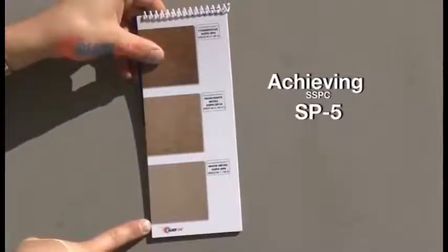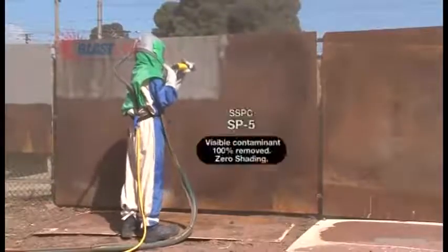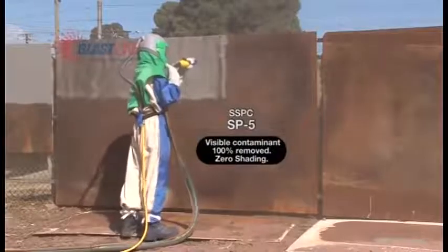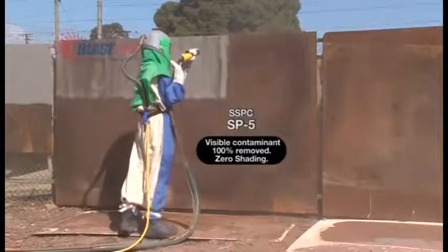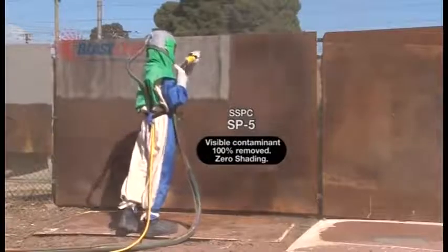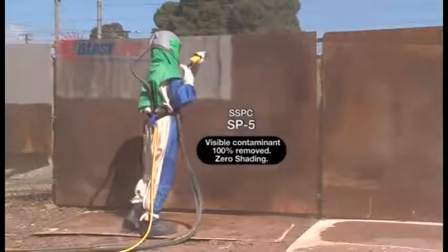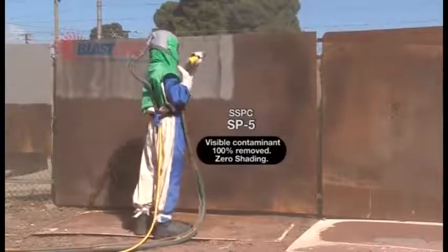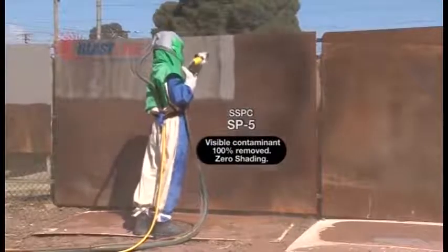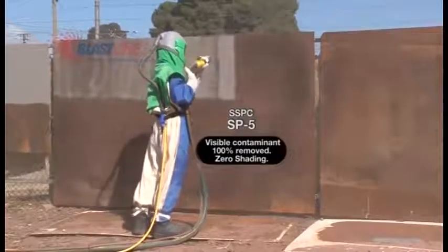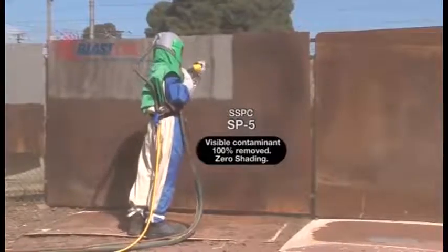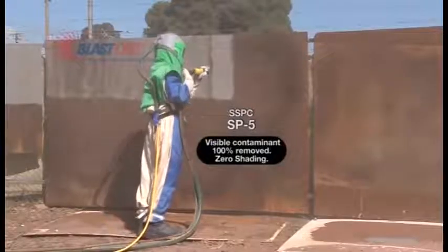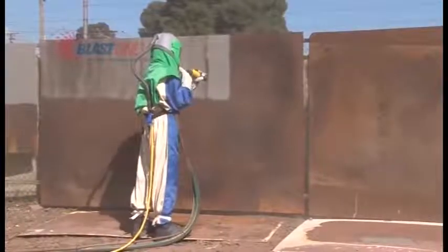How to achieve an SSPC SP5. The specification for SP5 requires a clean, consistent white metal blast with no visible contaminants or shading. To achieve a white metal blast on a grade C substrate, the blaster must move very slowly and much more deliberately, making sure there is overlap in his blast pattern.